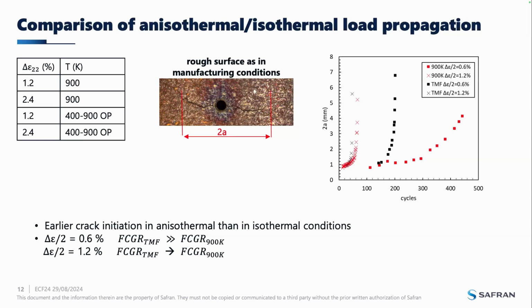So you have in red tests at isothermal condition, and in black tests at anisothermal condition. As you can see, crack initiation in anisothermal is earlier than in isothermal condition. And even if at 0.6% of strain amplitude, the factor is much higher for TMF than for isothermal, when the amplitude increases, it tends to be the same propagation speed.